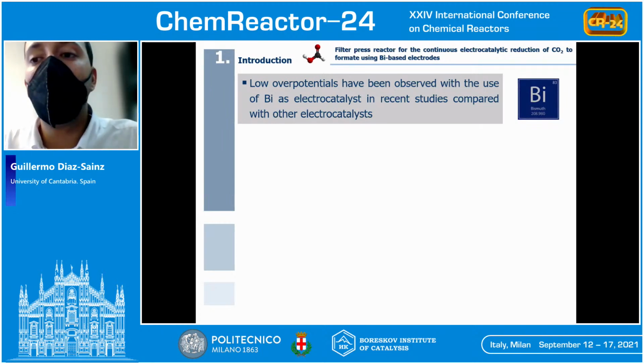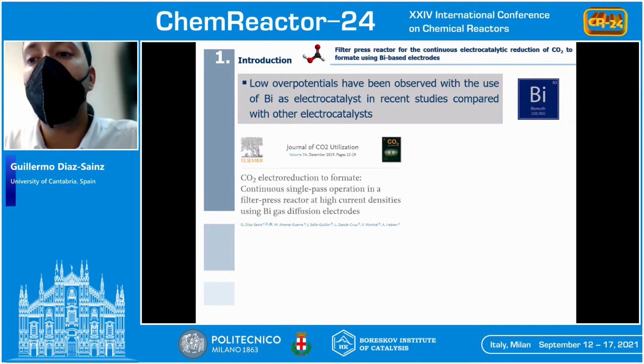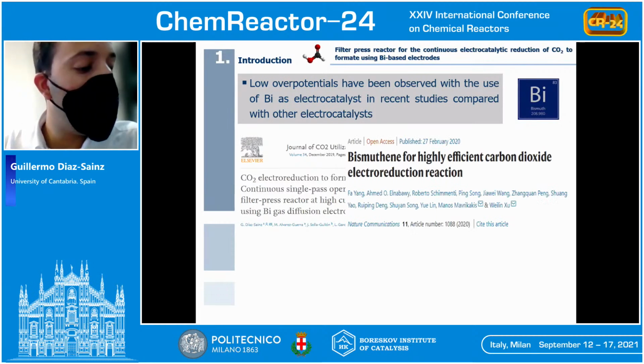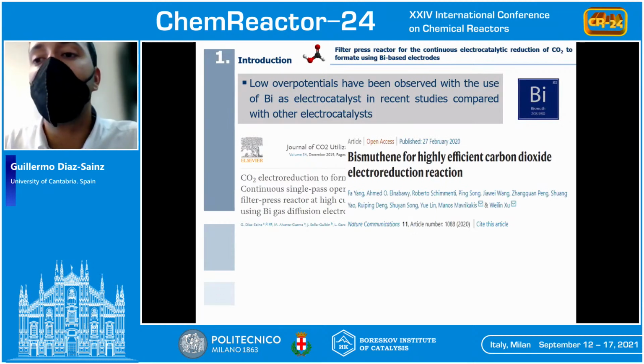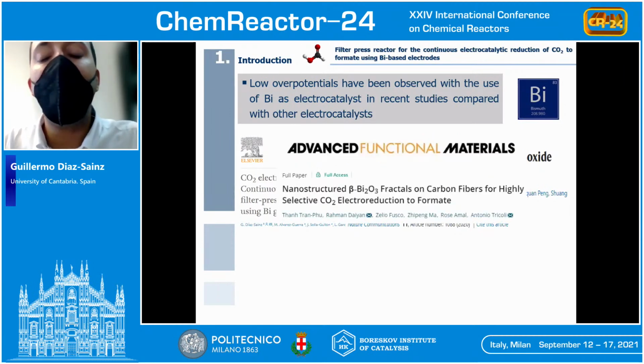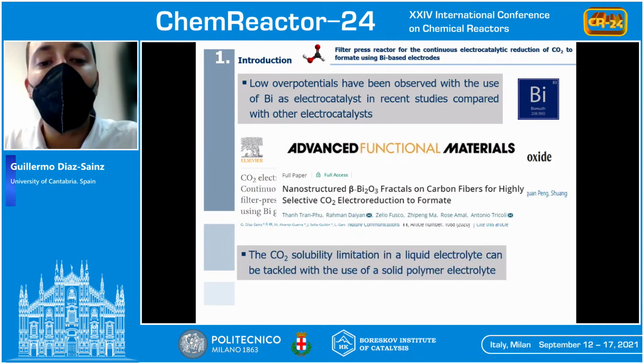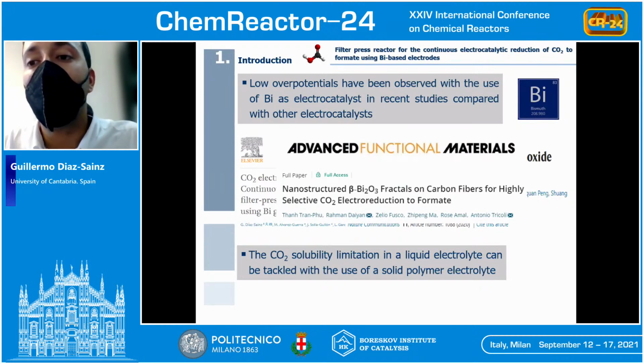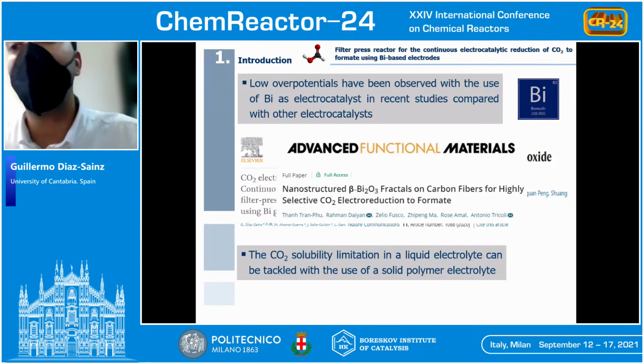In this context, it is very important to remark that recently a lot of studies have been published in the literature using bismuth electrocatalyst in the cathode for the electrocatalytic reduction of carbon dioxide to formate, because it has been observed that the use of bismuth reduces the overpotential compared with other electrocatalysts, such as lead, tin, or indium. In addition, there are some problems in this kind of process associated with the low solubility of carbon dioxide in liquid electrolytes. For this reason, in recent years there are many approaches using a carbon dioxide gas input stream in order to avoid the problems associated with the low solubility limitation in liquid electrolytes.